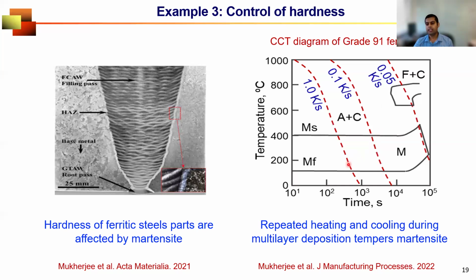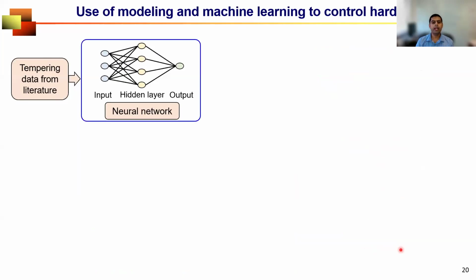We make additive manufacturing parts by depositing many layers. That means the layers that are already deposited will undergo repeated heating and cooling. And that repeated heating and cooling changes some of the martensite to tempered martensite. Hardness of tempered martensite is less than martensite. So depending on how many times it's getting reheated and cooled, the extent of tempered martensite formation will be dependent on that, and hardness will accordingly change. So how to model that?